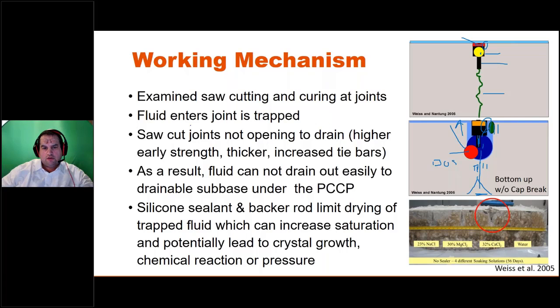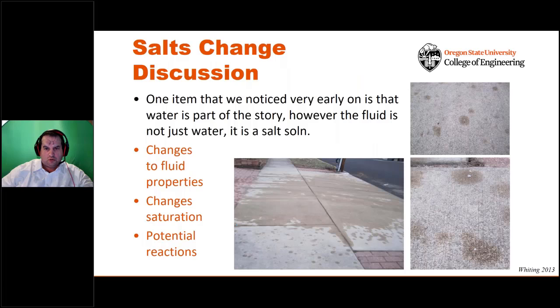So the idea here is fluid enters these joints, and I'm going to use fluid instead of water because it's going to be very concentrated in terms of the salt that we're dealing with. The joints are not opening as much as they needed to, and we're essentially getting this fluid trapped and it starts to react. As I mentioned, additionally, it's not just water, it's salt. And there's a couple things that are really important about this.